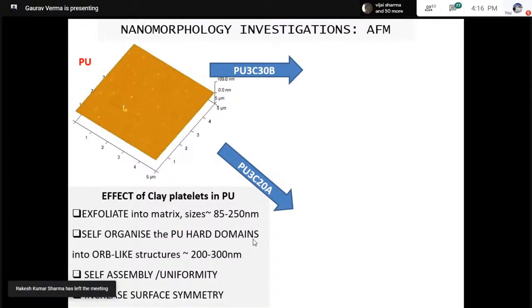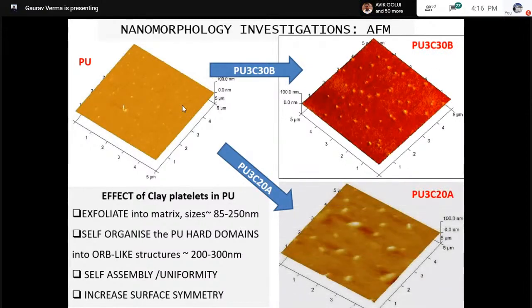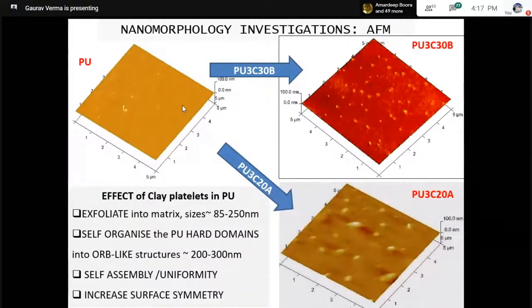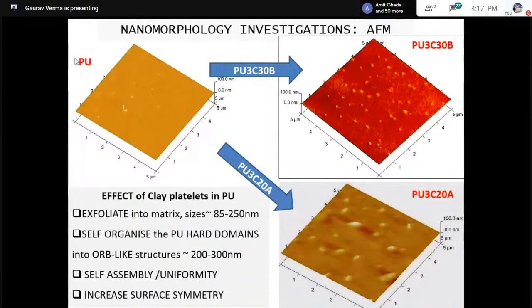And we also have to take up some questions for the discussion. A pristine automotive coating which you see on your left is turned into something very exciting, and this is a self-assembly of the hard segments of these coatings right onto the surface, which can be investigated or discerned by atomic force microscopy. And that is why I said if you have a tool like this with you, then you can do a lot of things, and you can understand that a pristine coating, when introduced with just 3 weight% clay platelets, can change the nanomorphology of these coatings.